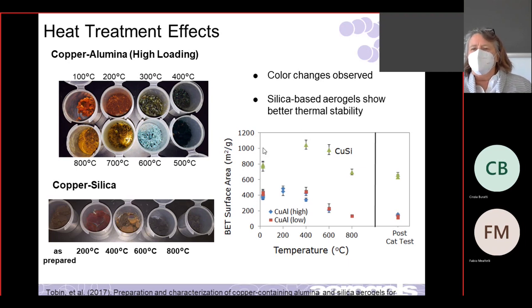And these materials, so the copper silica starts off really high surface area and it stays relatively high, above 600. The alumina starts off at about 400 meters squared per gram. And once you heat it above 400, it goes way down, like 60, which takes away a little bit of the advantage of, wow, it's high surface area. But this is a much higher surface area than the catalysts they use now, which tend to have 2 meters squared per gram or something like that. So we've lost the high surface area when we heat it. Not so much with the silica, but the silica is not quite as reactive as the alumina from a catalyst point of view.